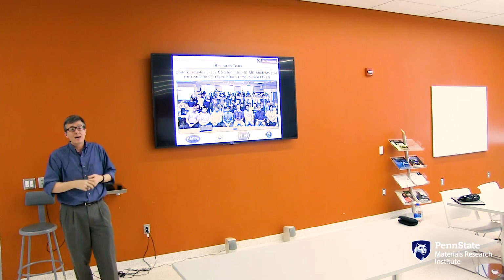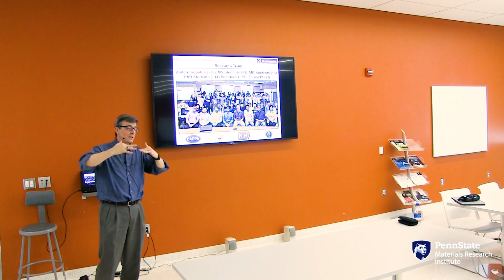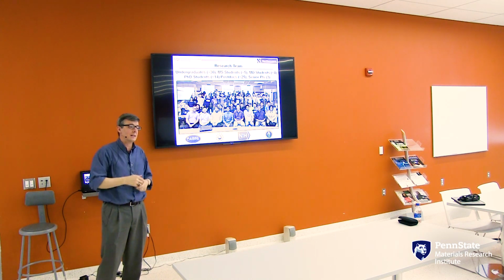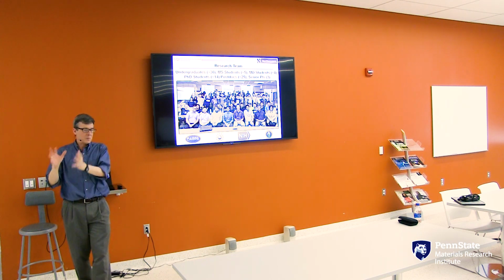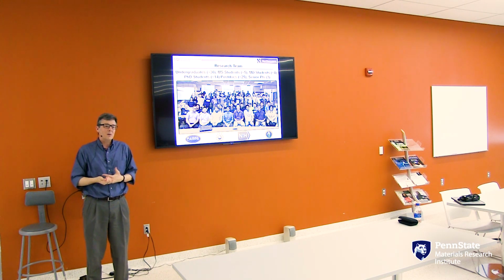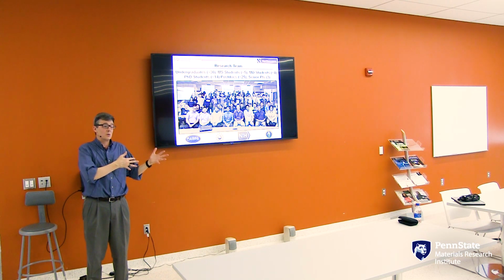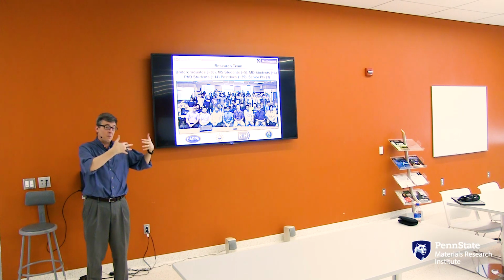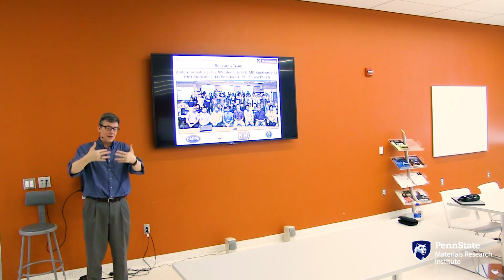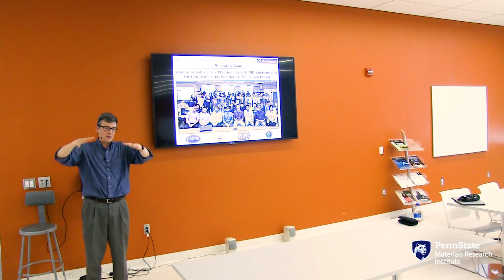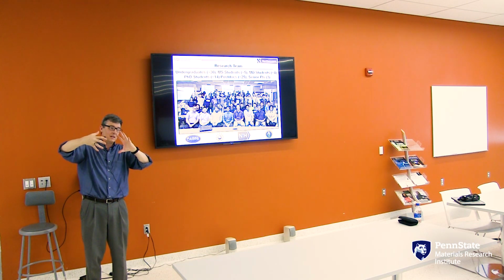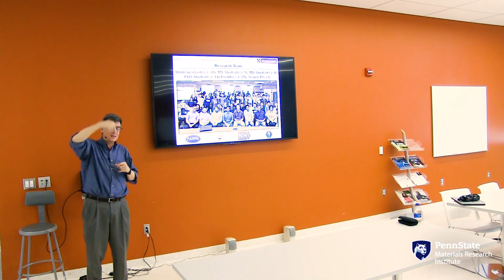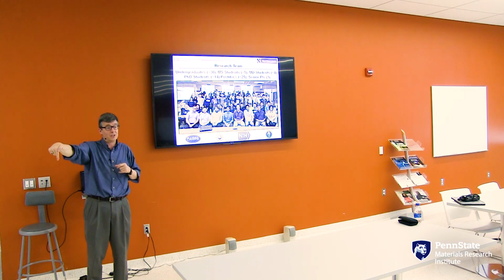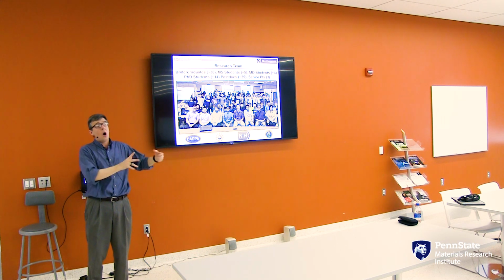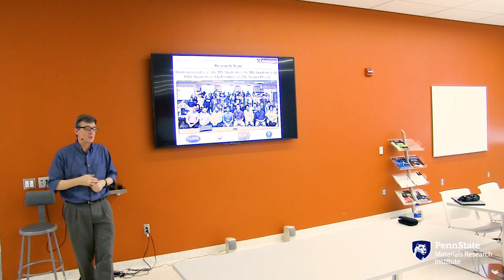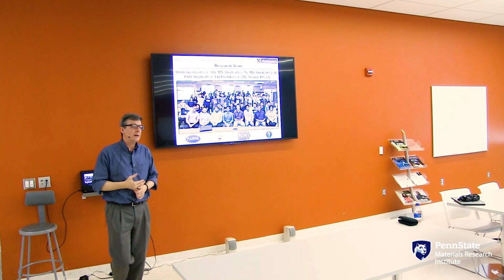So you have to do a lot of cyclical testing. We have all kinds of apparatus to bend over and over again and stretch and twist and things like that. So we study things at an experimental level using those kinds of approaches. But then we're also very closely coupled into Yonggang Huang's group. So we know from a theoretical mechanics engineering standpoint that we're developing a device that will offer this range of stretchability, this degree of bendability, this degree of ability to twist before we reach strain levels in the constituent materials that would lead to fracture or plastic deformation. So they're designed to be reliable up front over a certain range of strains, for example, system level strains. And then we try to validate that experimentally.